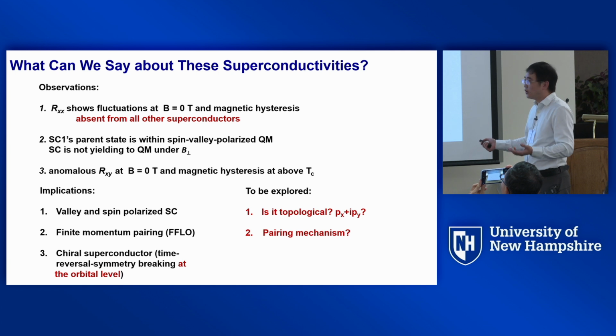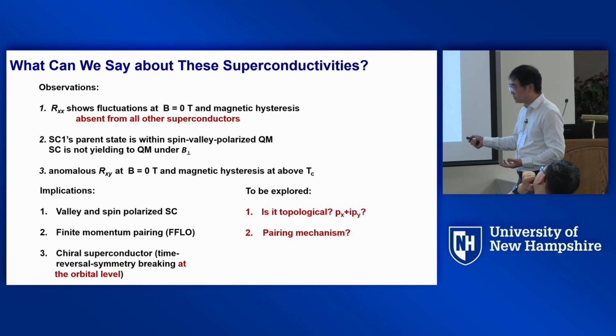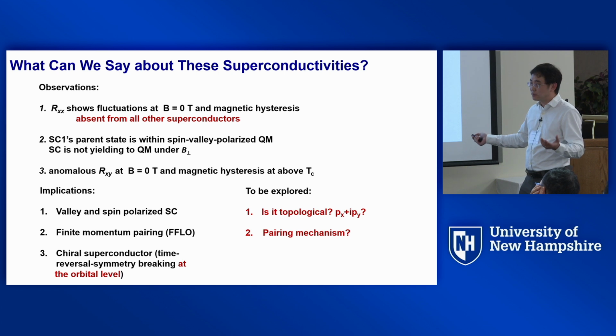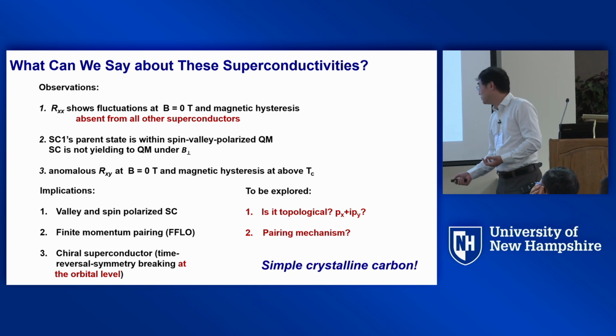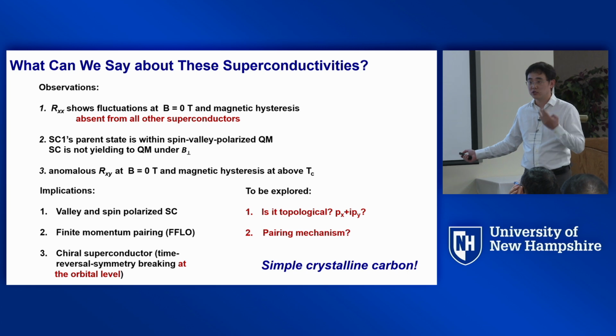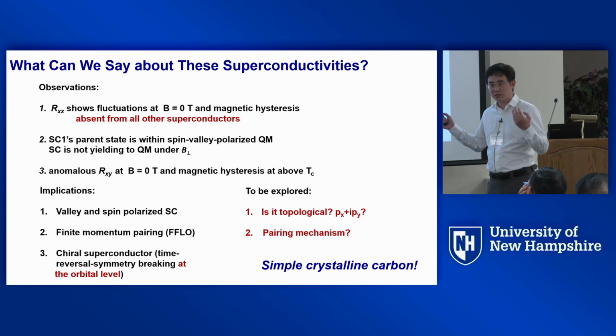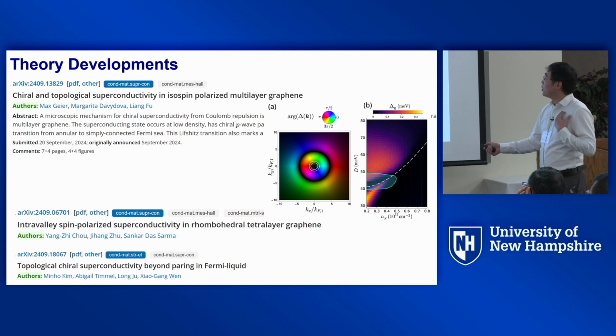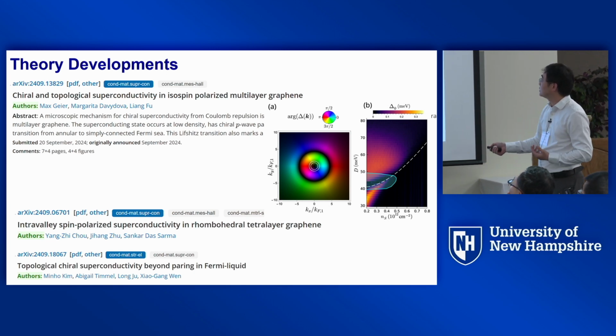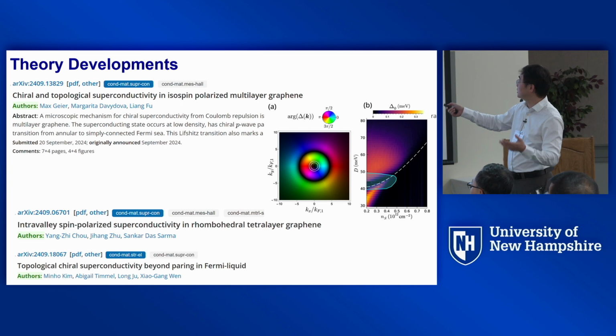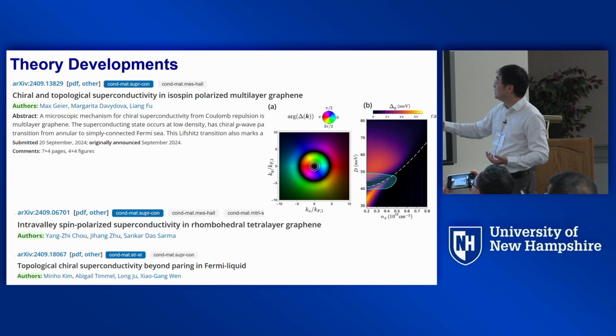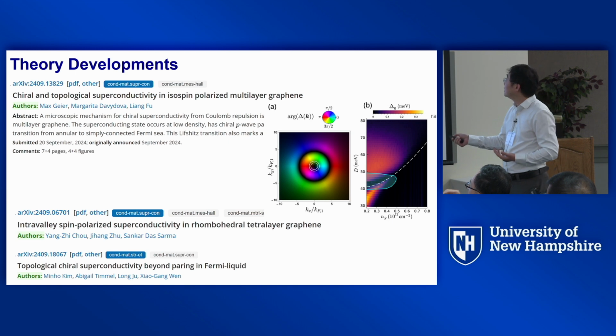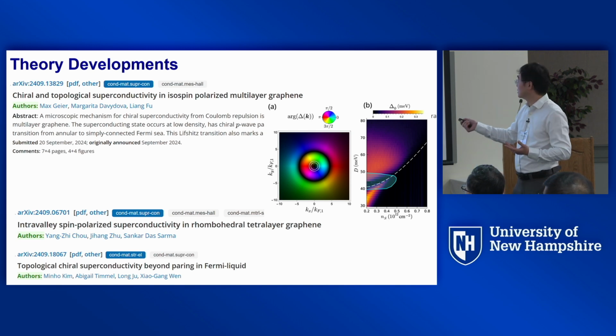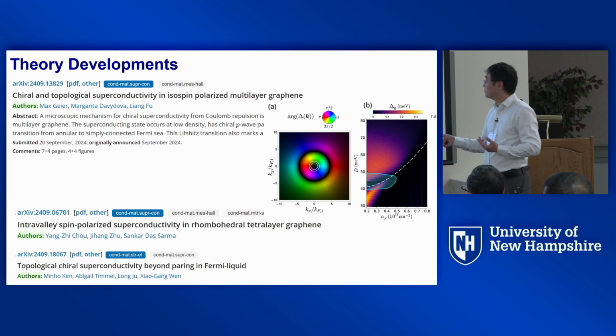And what we do not know yet at this point from experiment is whether this is topological, right? It has to be px plus ipy instead of p to be topological, and we don't know what the pairing mechanism is. But I want to remind you, this is a simple carbon. There's no moiré, there's no TMD, there's no SOC. It's just flat band. Okay? And I should point out that after the experiment, there are already several theory works looking at these problems. And if you just read the titles, you find that it seems people agree that this is chiral and possibly topological. This is one of our organizers Liang Fu's work that does show this calculation compatible with experimental observation. There's a phase winding of the order parameter.